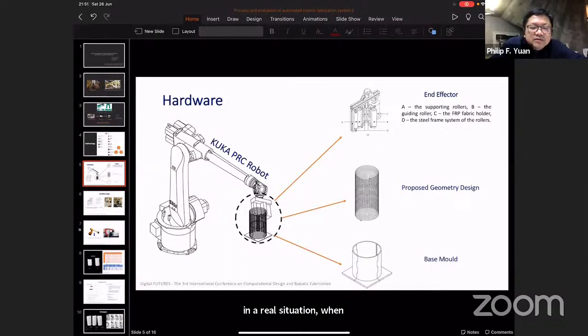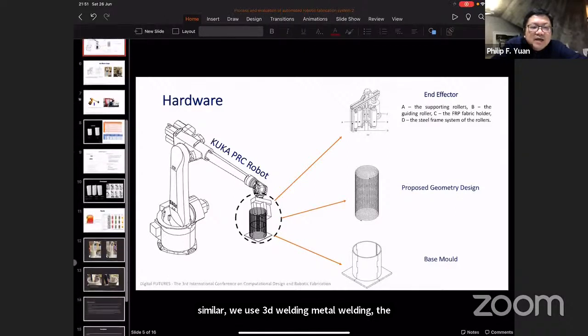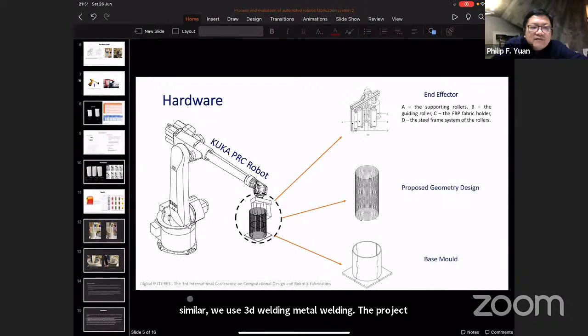3D print, each time you put material in the effector, the density, the humidity, and the proportion of the material are all different. It's really difficult to predict what will happen time by time, because of the water percentage, for example. The other situation is similar. We use 3D welding, metal welding. In the project, we find that when we have three or four different effectors, every effector has different performance. So when you set up a training data toolbox, it really needs a lot of time to understand the behavior and performance of each effector.